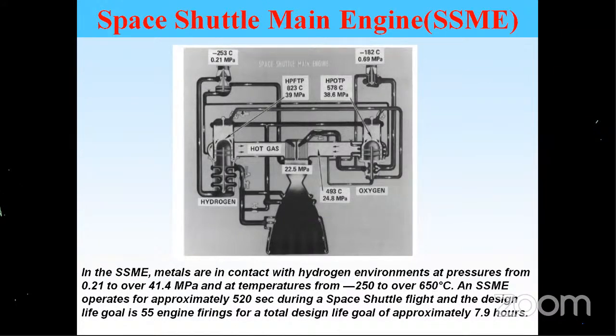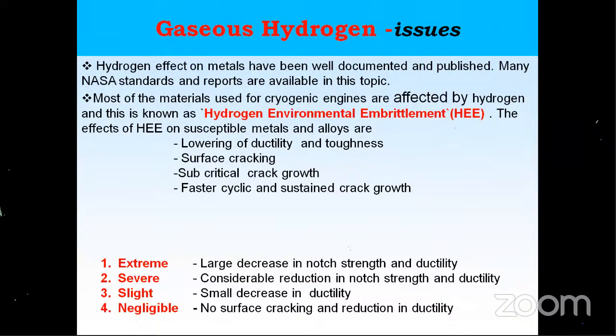Whatever I'm talking about is not that. This is exposure to hydrogen gas, either liquid hydrogen or gaseous hydrogen, GH2 or LH2. In the SSME, it operates for nearly 520 seconds in a space shuttle flight, and it is designed for 55 engine fires, with a life of more than 7.9 hours total. With internal hydrogen, the failure normally happens as delayed cracking. Delayed means hydrogen enters the material and after 1 or 2 days, or a week, or a month, it cracks and fails.